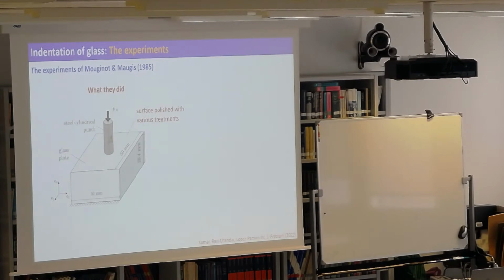Very interesting. They treated the surface of the glass with different sandpaper, and also with some polishing gels. What that does is you create roughness in the specimen, and that means that you create defects, if you like, inherent defects that are much larger on the surface than in the bulk. Glass can have very tiny defects. That's why it's so very strong. But if you start to mess around with the surface, you start to scratch it, well, you're going to make it weaker, right? So the strength surface is the macroscopic manifestation of the presence of inherent defects in the material. Materials break at a finite value of stress because one of those defects is going to go, right? So this is a macroscopic theory. We are not modeling defects explicitly. We are modeling defects implicitly through their macroscopic manifestation, which is the strength surface.